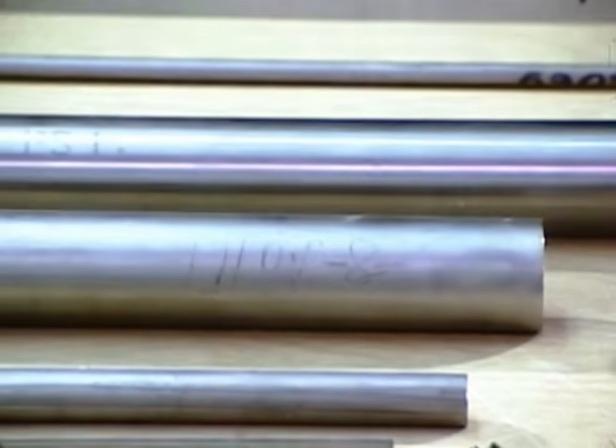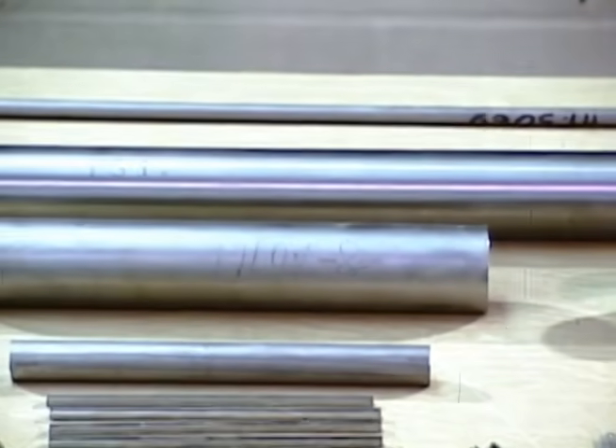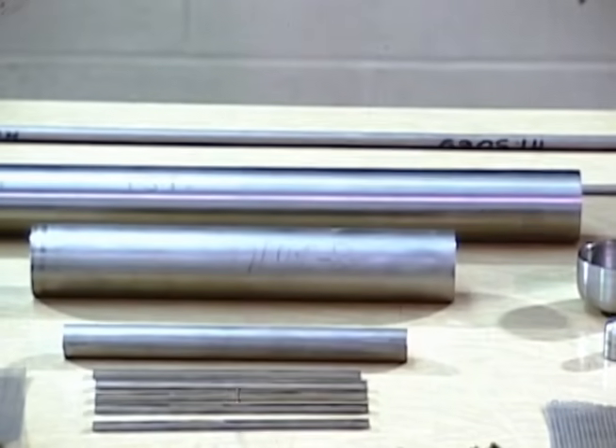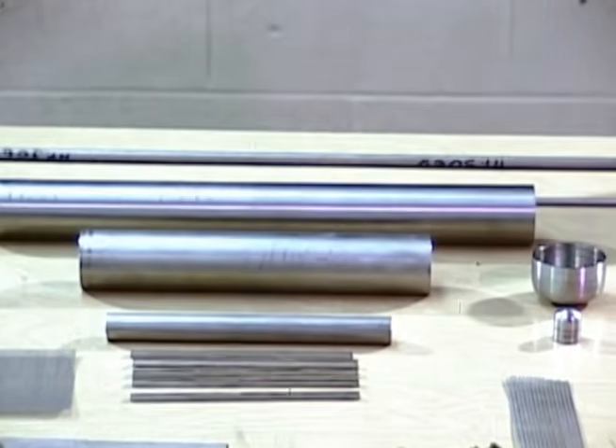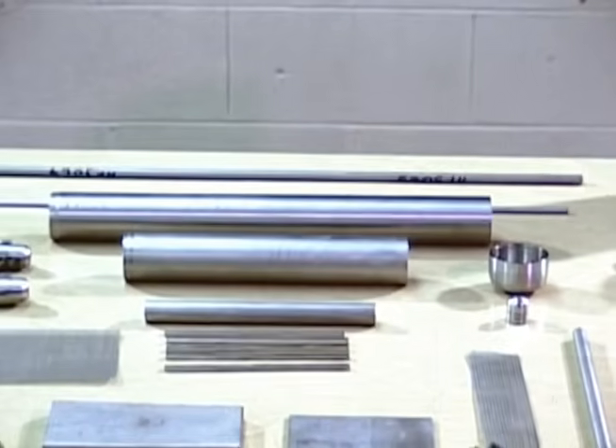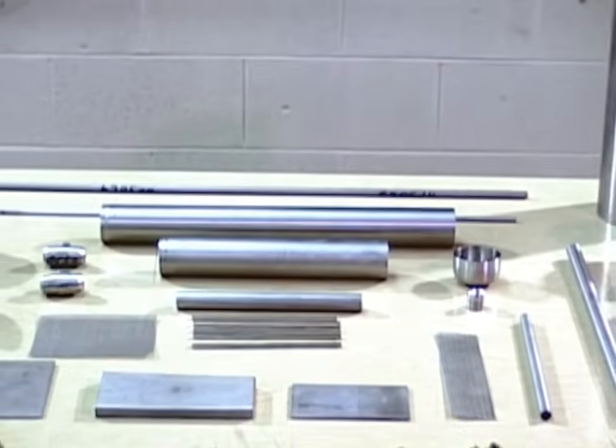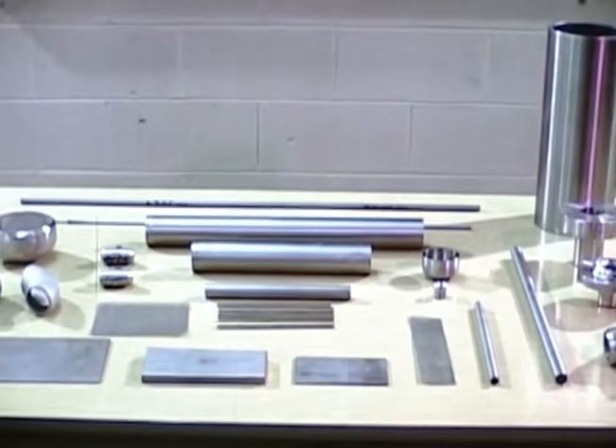The salt-containing piping and components are fabricated from Hastelloy N, a special nickel-molybdenum alloy developed at Oak Ridge, which has good resistance to corrosion attack by fluoride salts up to 1500-degree temperatures.